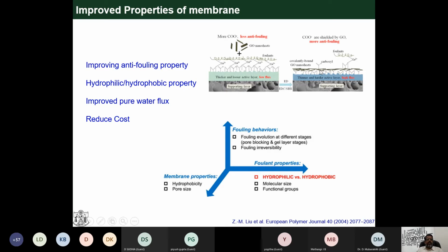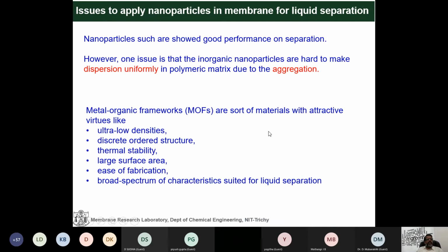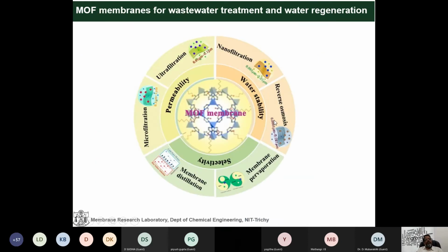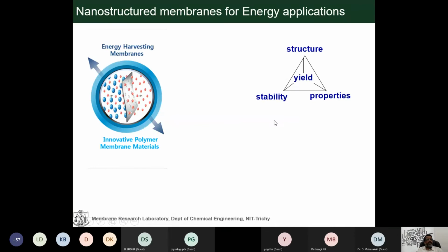But here, the carboxyl and covalent bond of graphene oxide monolayers on the surface of the membrane don't allow attachment of foulants on the surface of the membrane. If they don't allow the attachment of foulants, you get high flux compared to this one. This is less anti-fouling, and this is more anti-fouling. Then this is called materials for unique liquid separation. I won't go much into that.